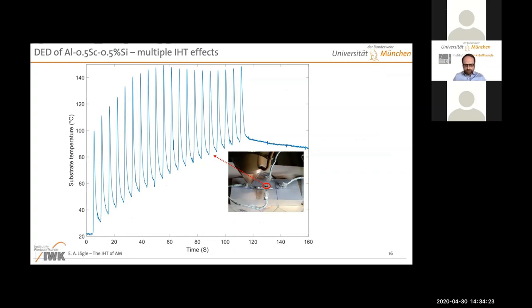So we're back at DED, and this graph I've already shown to you. The material that we're looking at here is, again, a model alloy, but not a steel. Coming from the Max-Planck Institute for Iron Research, of course, we love our steels, but in this case we're looking at an aluminium alloy. Perhaps you are aware of the Scalmalloy, the commercial alloy which is used in additive manufacturing quite a bit at the moment. And this here is basically a stripped-down Scalmalloy with the addition of silicon. So 0.5 scandium, 0.5 silicon, a simple ternary alloy.